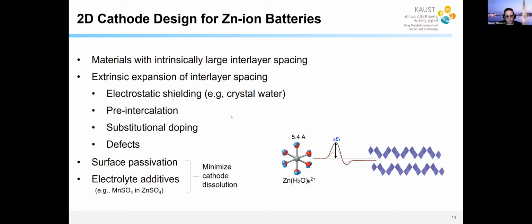But then, you know, what requirements do you want from a 2D material? So it should have intrinsically large interlayer spacing to be able to accommodate the zinc. But let's say it doesn't. Some materials have other desirable properties. They are stable, they are cheap, they're abundant, they don't dissolve in electrolyte, but their interlayer spacing is not big enough. Actually, molybdenum disulfide is like that. So we need strategies to expand their interlayer spacing, maybe some electrostatic shielding, pre-intercalation, doping. Other strategies for the electrolyte, people actually use surface passivation or they use electrolyte additives.